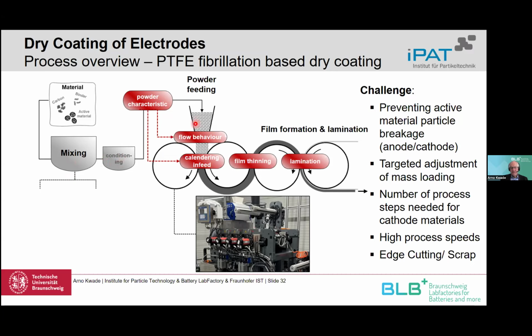It has to be fed then into, for example, a calendering machine, which is the most common production way today, but I will show you a little bit later also other possibilities. And then you form the film, and usually you have to go through several rolls to come to the final density and also final thickness of your electrode, and then you laminate that on an electrode. So it sounds simple, but it's not that simple because a lot of parameters affect this process.